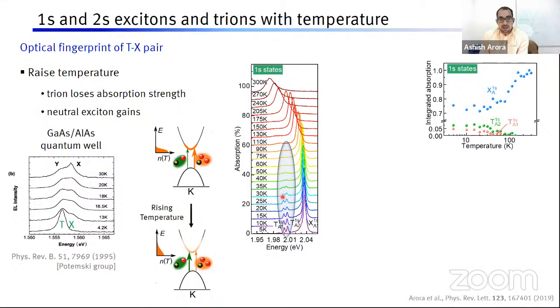Now, here are the ground state trions, these two features, and there is this ground state exciton. When we raise temperature, this is absorption. When we raise temperature, we see that these ground state trions lose oscillator strength. Whereas in exciton, if we calculate the area under the curve, which is the measure of oscillator strength, it rises. So what we see is the integrated absorption for the ground state excitons rises as a function of temperature, whereas for the trions, it goes down.